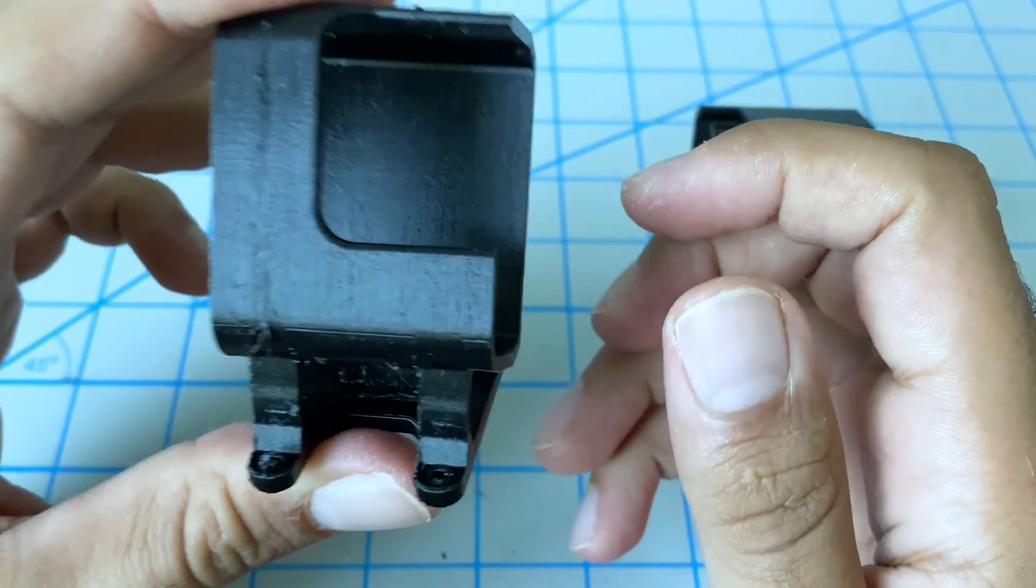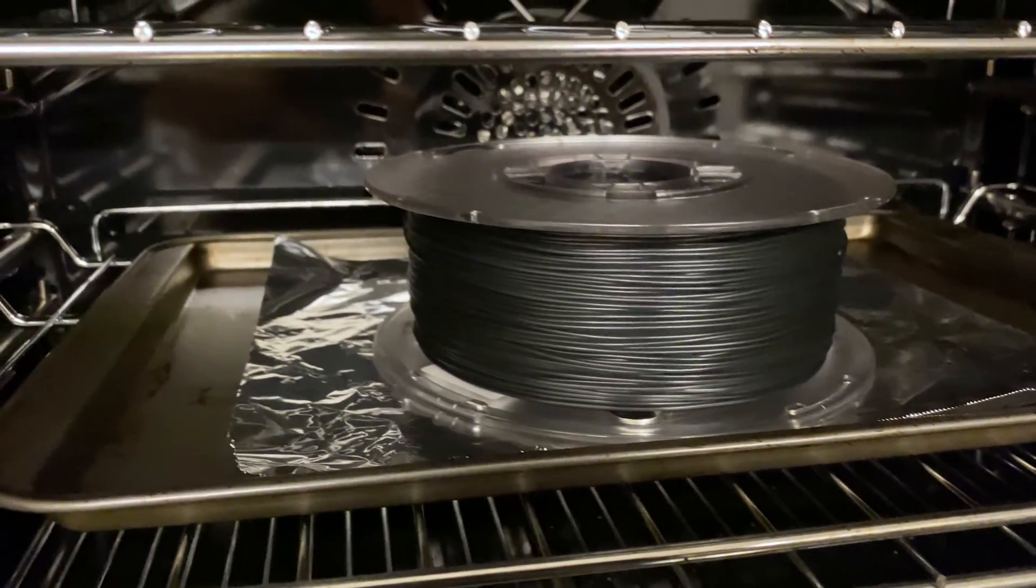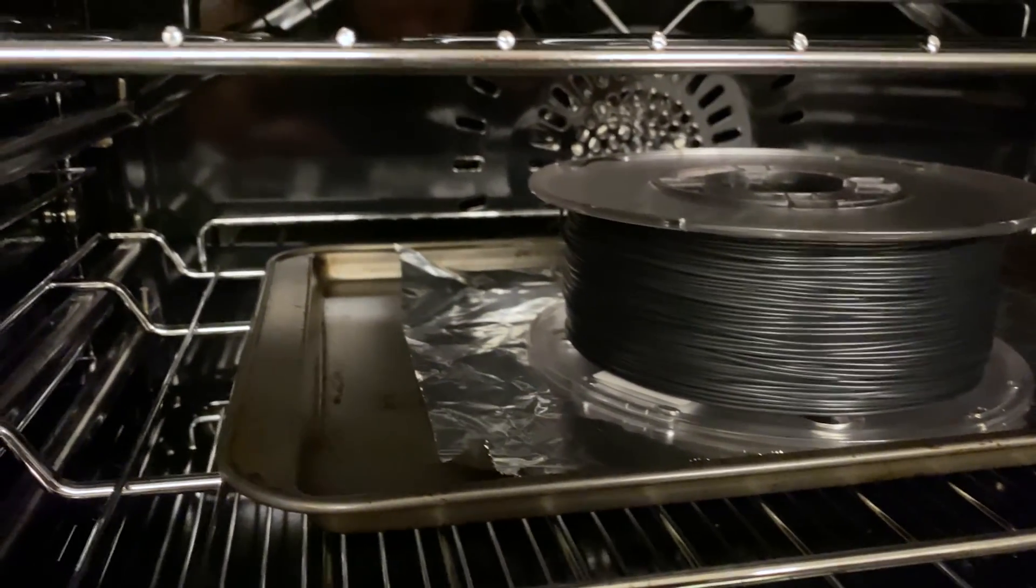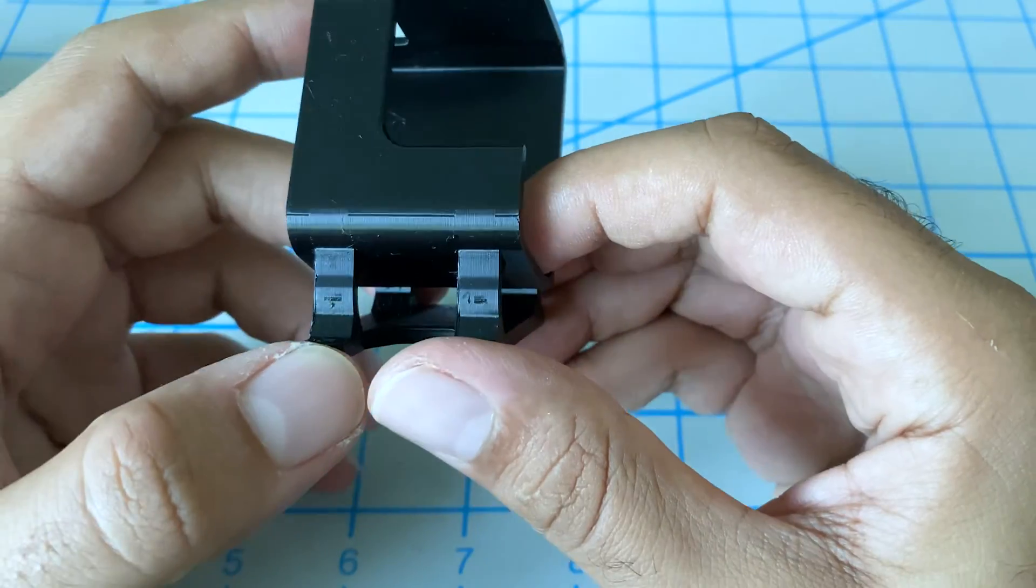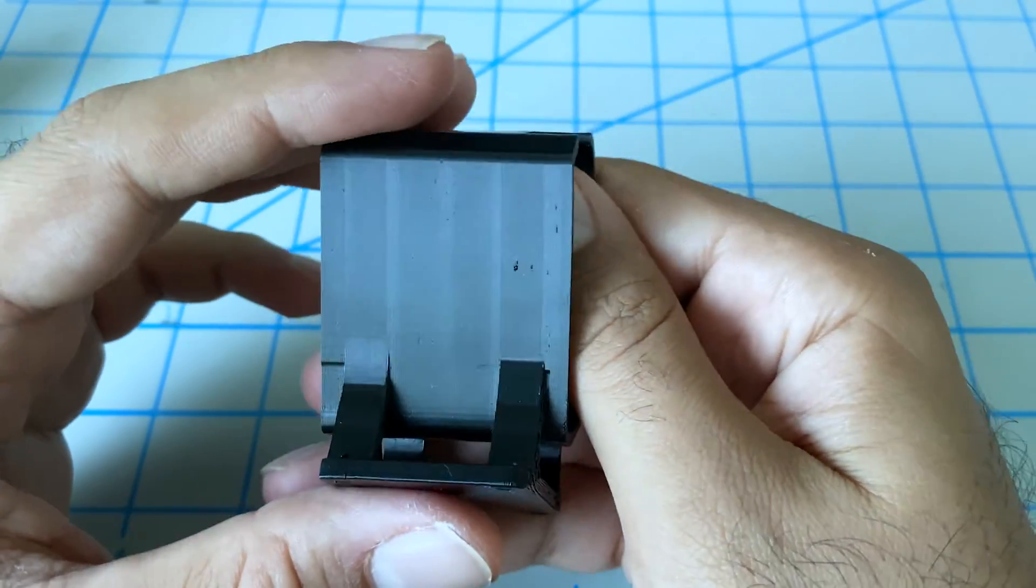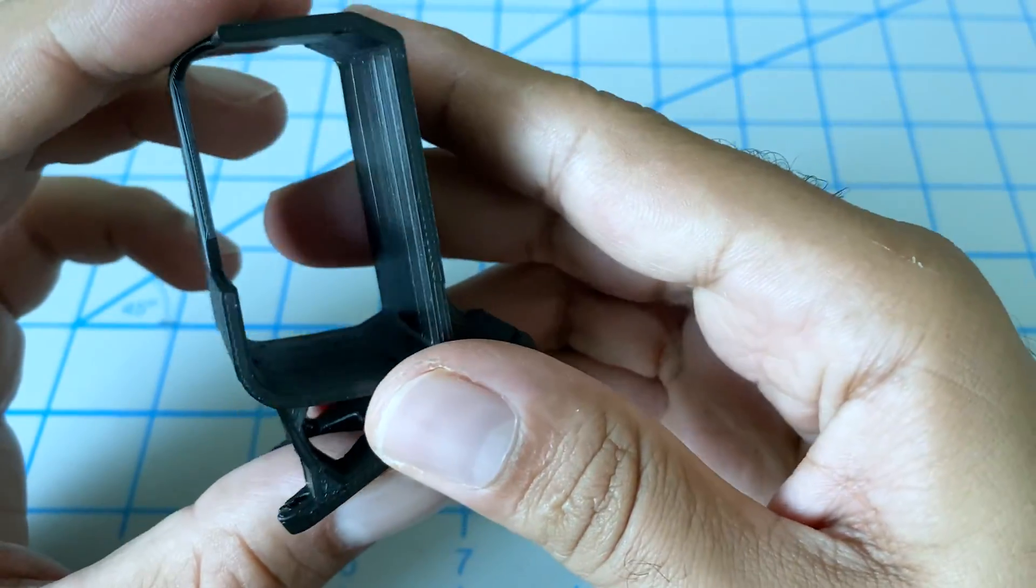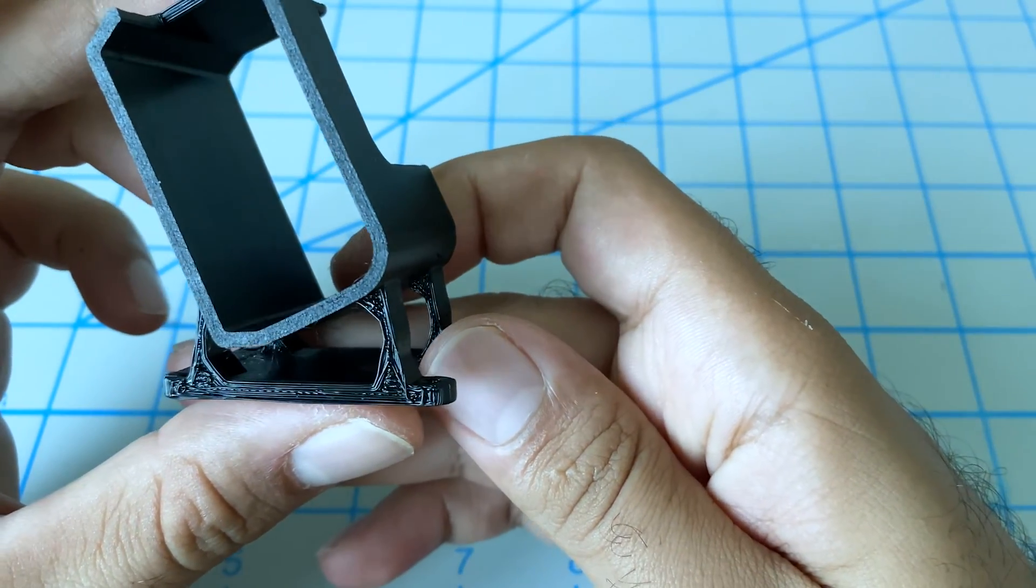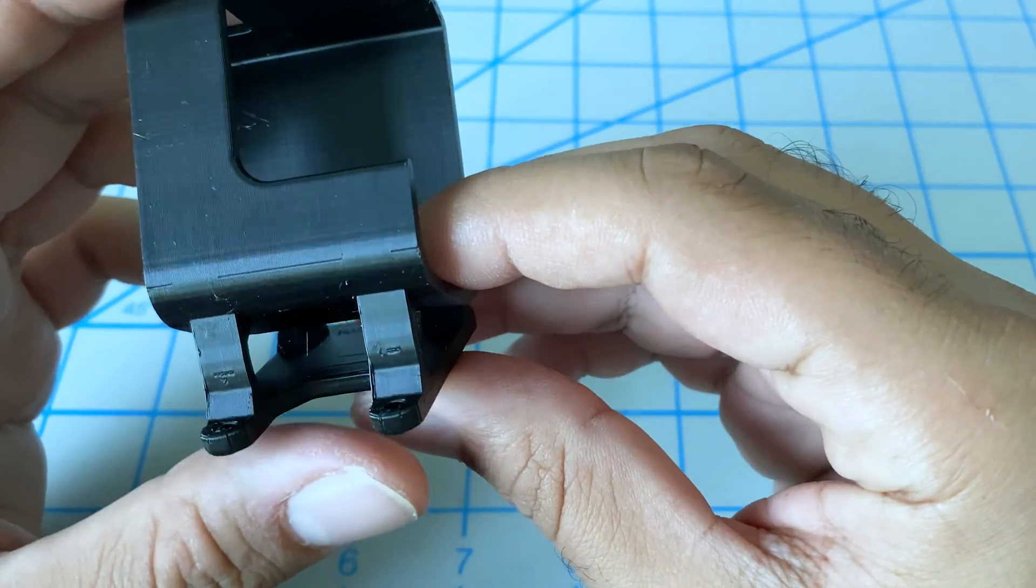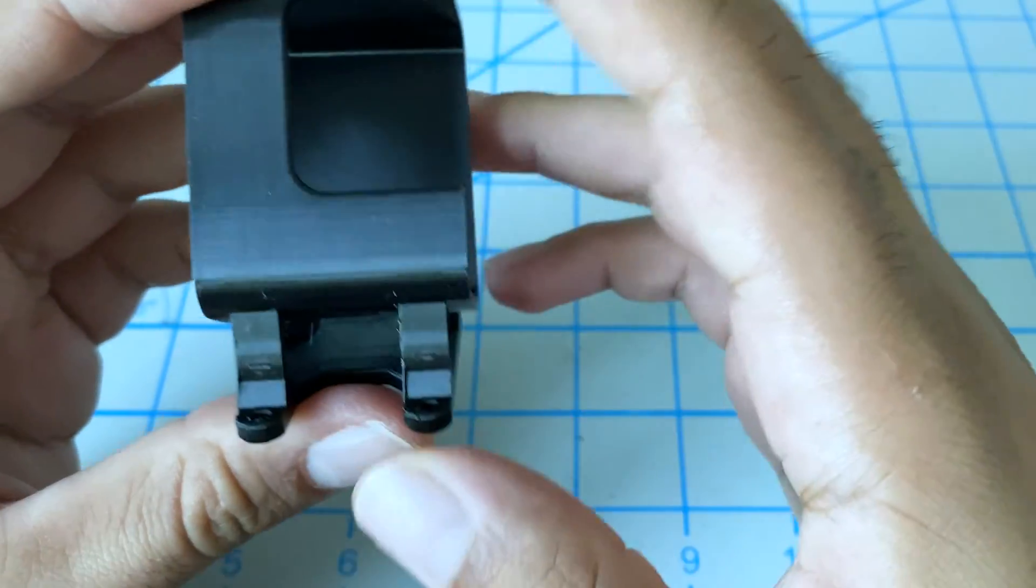And after printing this, we put the filament in the oven at 160 degrees Fahrenheit for one hour. And no changes to the file, this is what came out. And we can see here, not as good as the first one but fairly smooth. Not too much stringing. And honestly I think if we left it in the oven for maybe another half an hour it would have been even better.